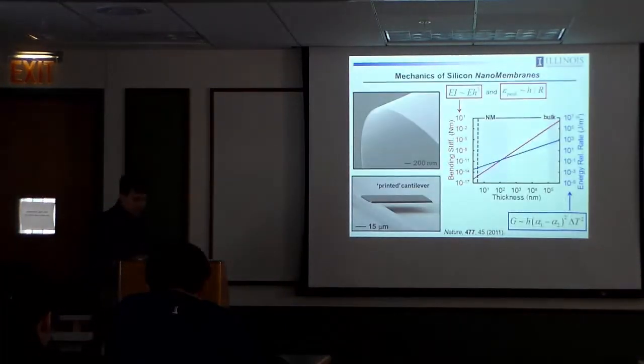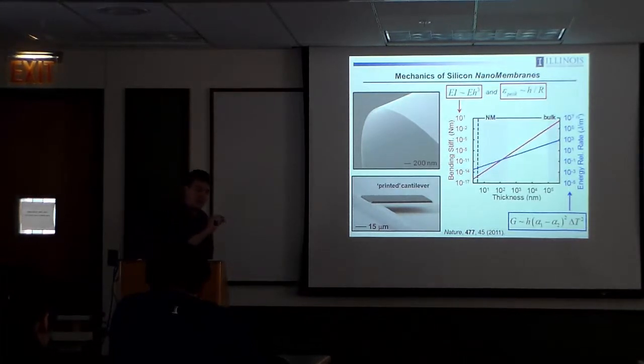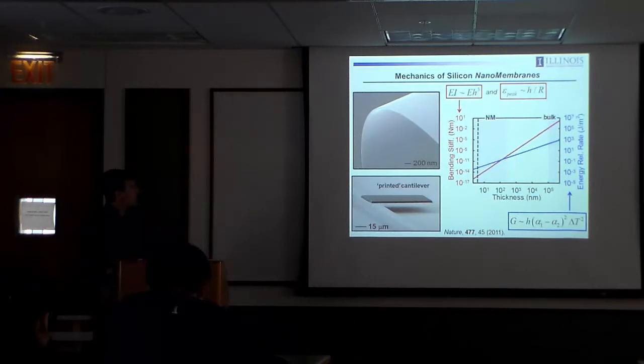So if you think about this format of material, it has the properties that I just mentioned. It's very planar, flat. It's rigid and brittle. If you drop it on the ground, it'll shatter into a million pieces. If you try to wrap it around a body part, it will crack. And that's partly because of the intrinsic materials properties, but it's also a consequence of the fact that the wafers are pretty thick. So maybe a half millimeter thick or a millimeter thick, depending on the diameter.